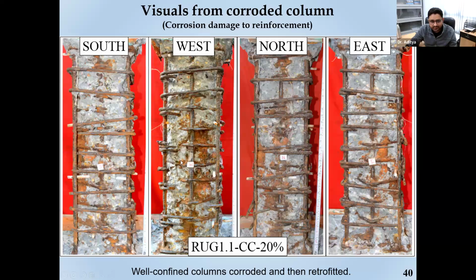Here, if you will see in this 20%, some of the bars got completely lost, and therefore we can always say that the response of the corroded column is obviously a function of the corrosion itself, its distribution, and all those things, which is very random. But still, to reach a conclusion for an existing structure, which I just showed you during the case studies, what should be our approach? How should we go about it? We'll have to somewhere quantify the corrosion that is present in the structure, and then do a retrofitting. And that retrofitting should be validated at some forum. So that's one way of doing it.